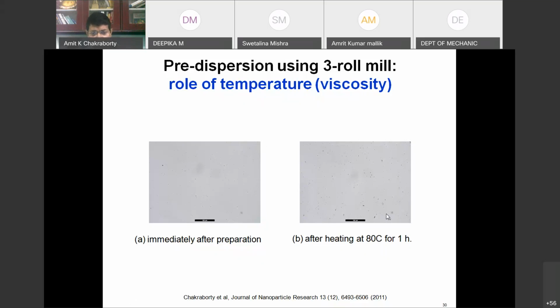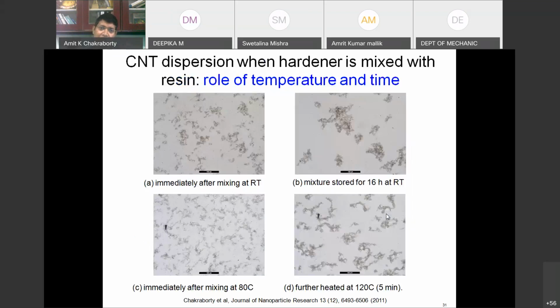So we must ensure that if we have got a very good dispersion of the CNT in the matrix, the dispersion is stable over the entire process of curing, for 6 hours or 8 hours at 120 degrees Celsius. If that is not happening, then we are unlikely to get any improvement. That is actually what we found out: after some time, if you heat, particles start to agglomerate. Another study looked at the influence of temperature and time together.